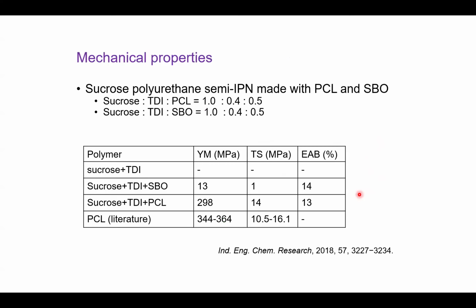And just to prove that you get benefit from it, this will be sucrose, TDI, and polycaprolactone, as well as soybean oil at 0.50% level for the second polymer. Sucrose plus TDI, you can see this will be mechanical strength: yield modulus, tensile strength, elongation at break. Sucrose plus TDI is very brittle, you don't get any value. If you add soybean oil, you already get some values. They're not very high, but you get some values. If you add polycaprolactone, look at that. You get very nice values.